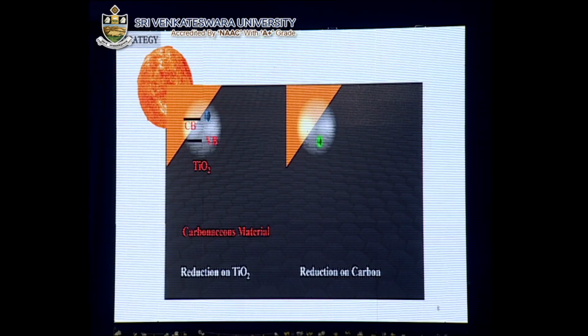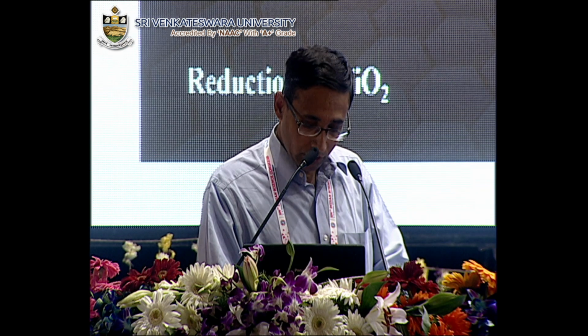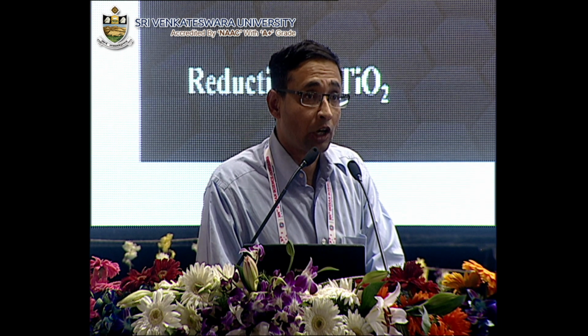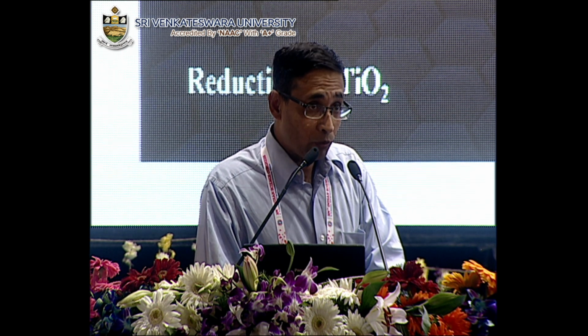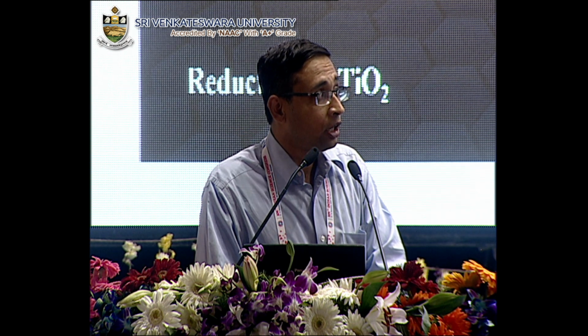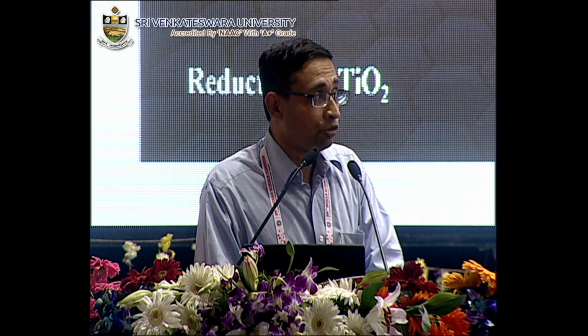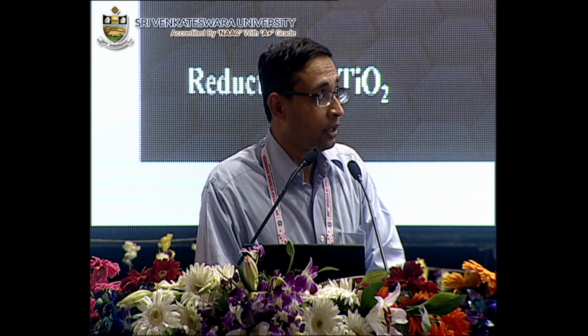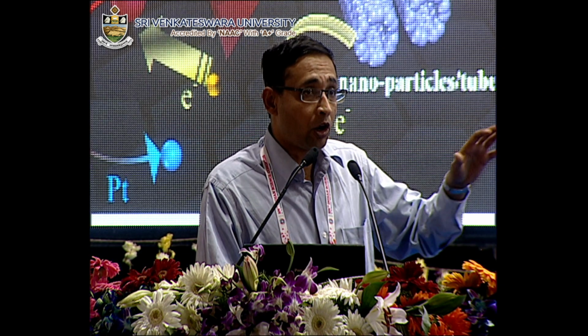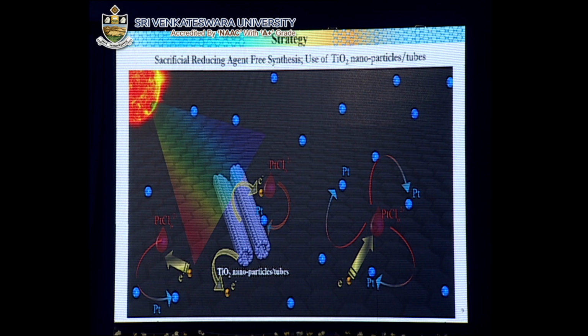Now, the excited electron also travels onto the carbon, because carbon has a similar band structure to that of TiO2. Instead of traveling within itself, the electron travels down to the carbon and reduces the chloroplatinic acid available on the carbon sheet. So our idea of preparing an electrocatalyst by using the excited electrons of TiO2 is achieved here. Platinum gets loaded onto the carbon all over the surface in a uniform way.